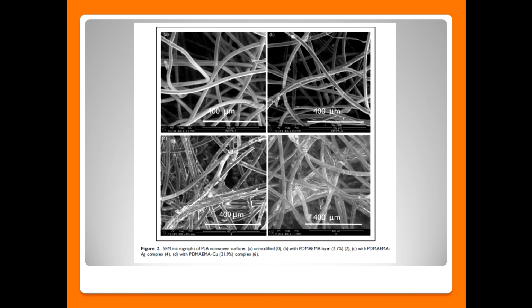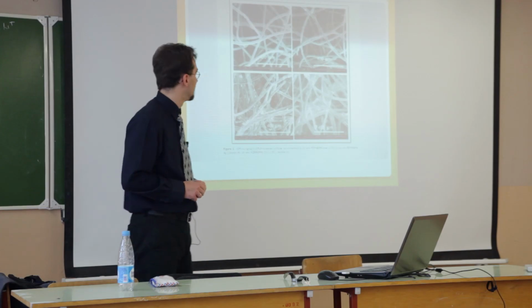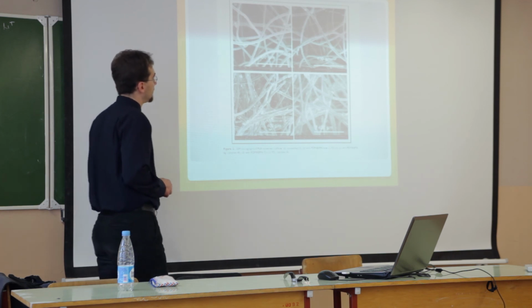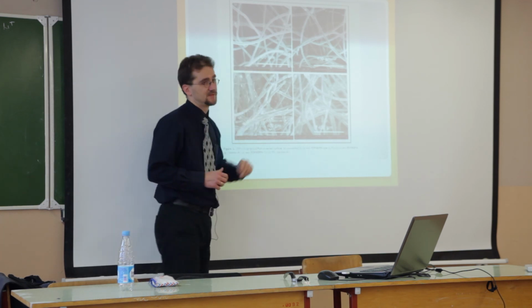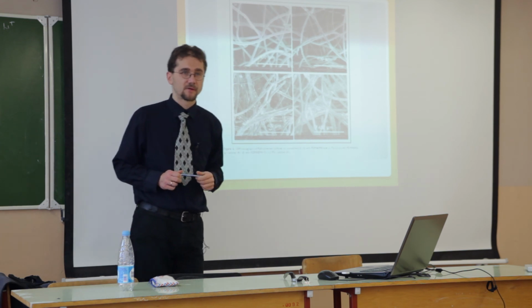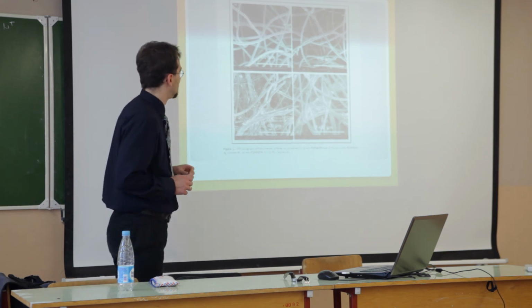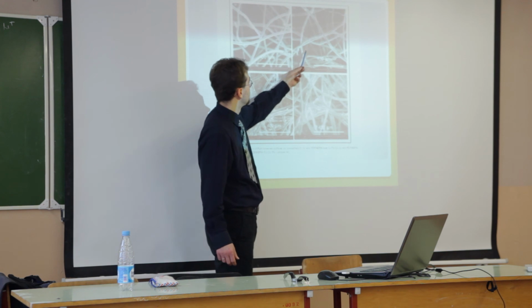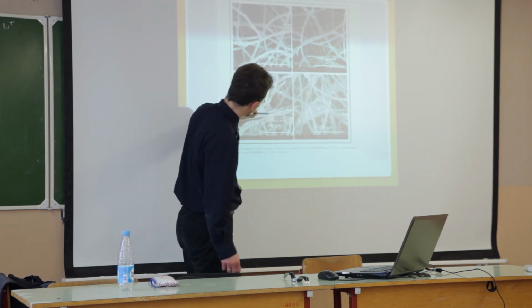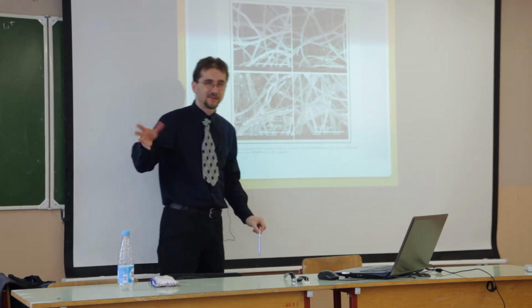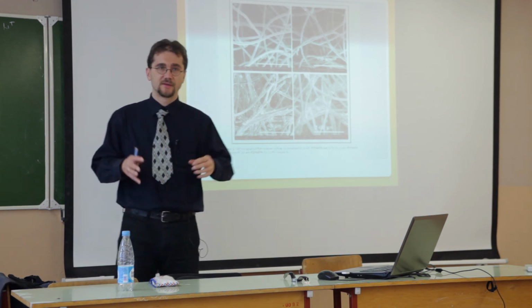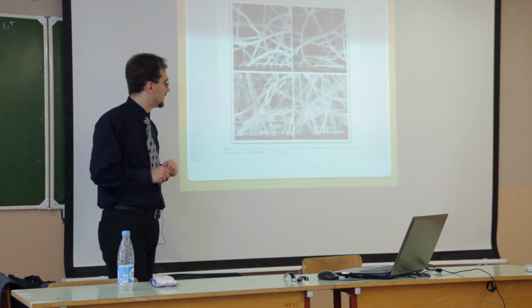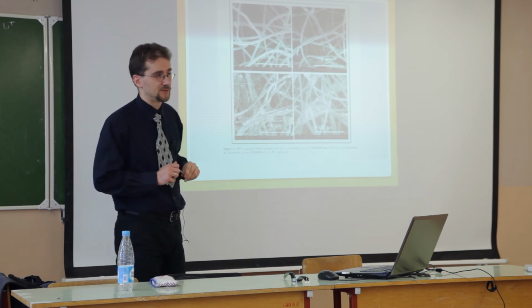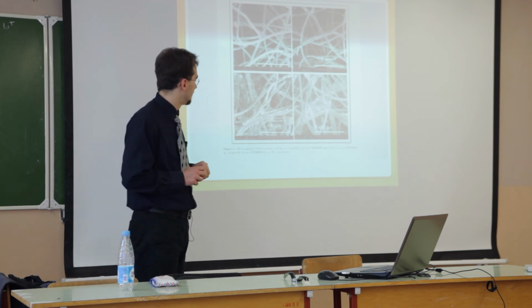Structure was also controlled by SEM microscopy. You can see before modification, this is a very regular structure. After modification, after one stage of modification, we can see some irregularity. Here it's completely different - the fibers are connected to each other using the modifier, but that's possible because we have a lot of modifier here.